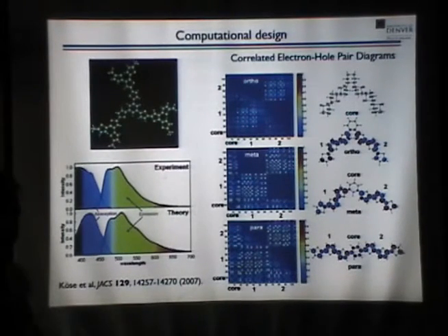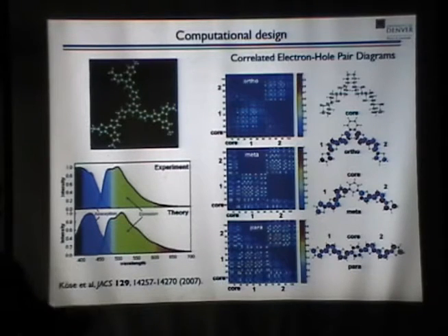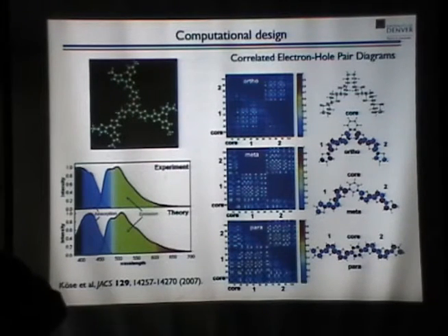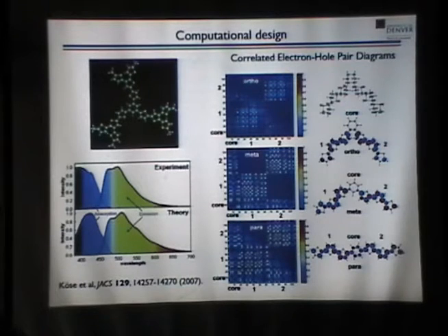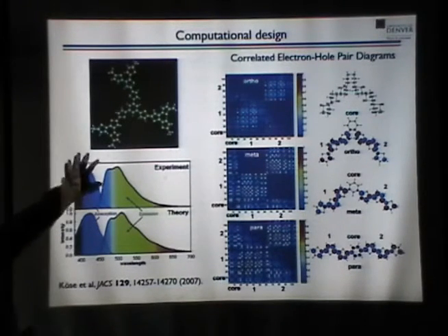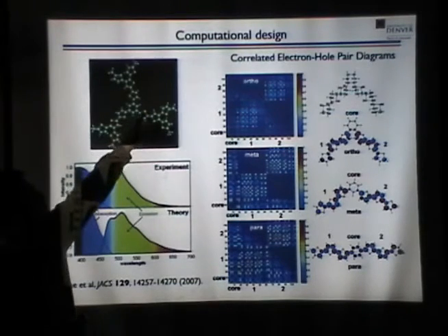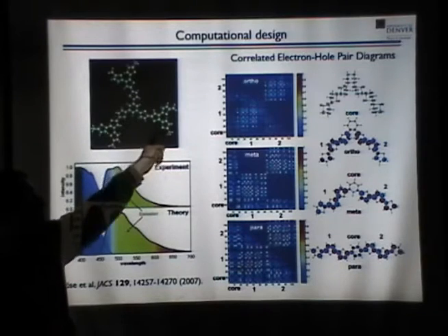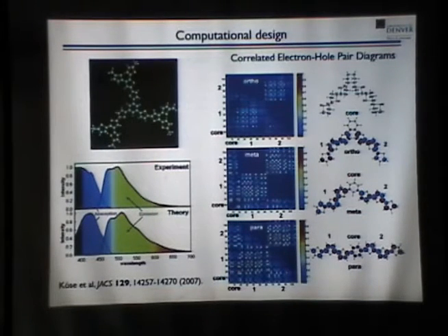One of the important things is, when we start assembling these molecules, we can put different monomers in, we can put different arms on the molecule. We want to know how the exciton can delocalize across the structure. One set of materials that we've been looking at is called a dendrimer, where we have a core group, in this case a benzene, and then we have arms, in this case made of thiophenes. And we can control the number of those arms and the length and the position.